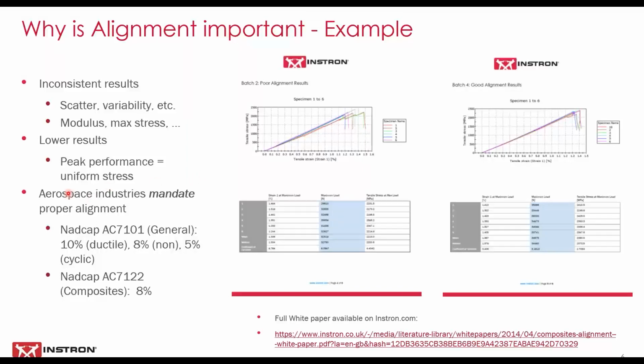In some areas, particularly aerospace, they're working on the regulatory framework, which would include NADCAP type checklists and requirements. So you can see that in general for metals testing, NADCAP are defining 10% bending strain for ductile materials, 8% for non-ductile, 5% for cyclic fatigue type work. And again, in the composites area, we're looking at say an 8% limit on bending strain.